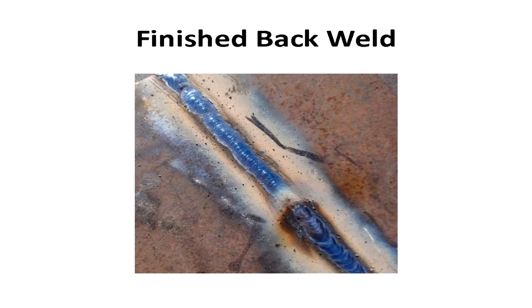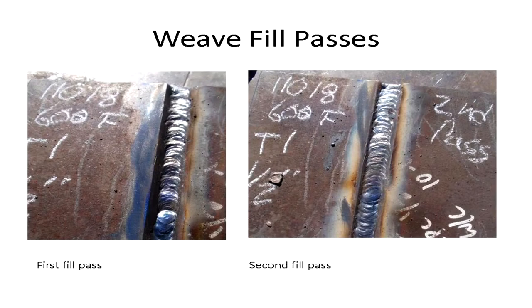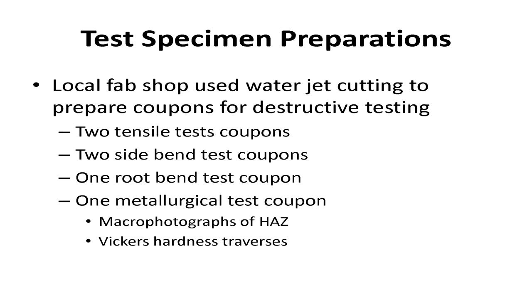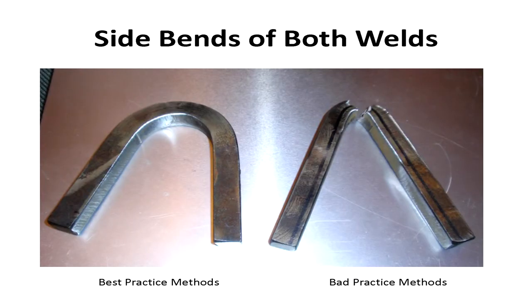There's the back weld. There's the first fill pass on the back side, second fill pass. Then I cut these coupons out of each one of them with the water jet. And we'll show you those. There's the side bend one, best practice. Didn't even bend this hard. Look at it, snapped it.